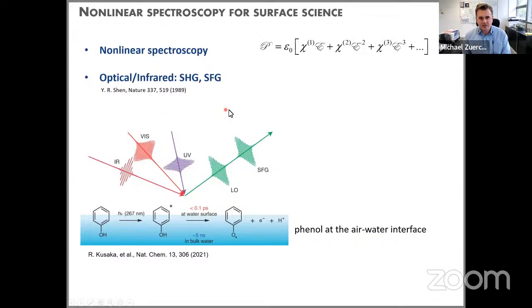Well, a very brief introduction to that area is that if we have a light pulse, described by its electric field, interacting with a medium, we can model the polarization response of the electrons in that material by this power series, where basically we can develop the polarization by different orders of the electric field. And in nonlinear optics, we know that this gives rise to the generation of new frequencies. One prominent example is second harmonic generation, where the second order term causes oscillation of the emerging electric field at twice the frequency of the incoming electric field. Other such second order processes involve, for example, sum frequency generation.